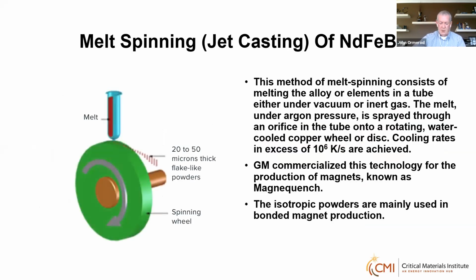Okay, let's move on and talk a little bit about the General Motors or Magnequench process. And here they pioneered the use of melt spinning. Now, melt spinning consists of melting the alloy or the elements in some sort of tube. That melt is then sprayed onto a rapidly rotating disc or wheel, typically water cooled, and cooling rates in excess of 10^6 degrees per second are achieved. Now, General Motors or Magnequench commercialized this technology, and it's primarily used today for producing isotropic powders that are mainly used in bonded magnets.